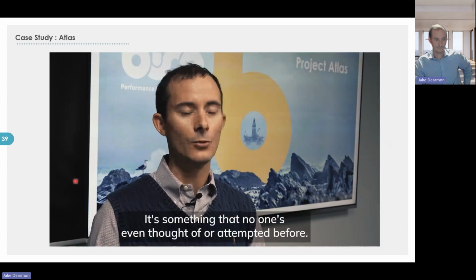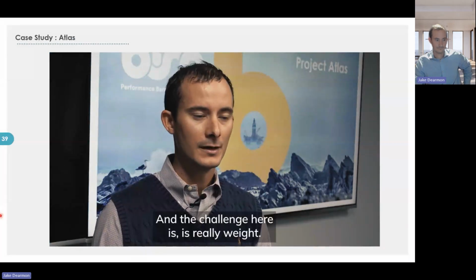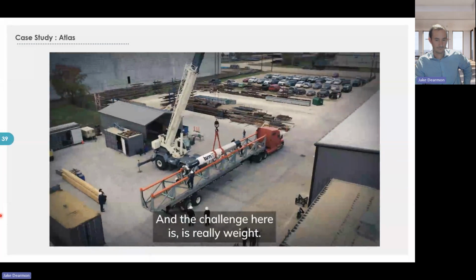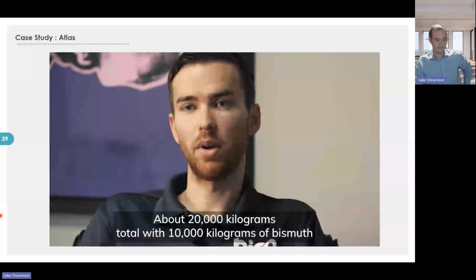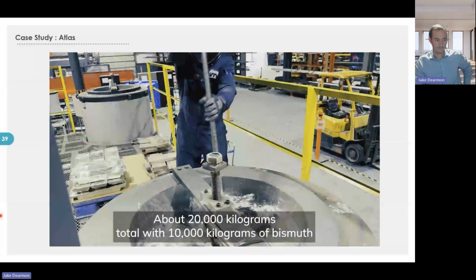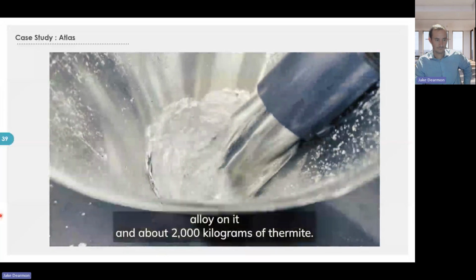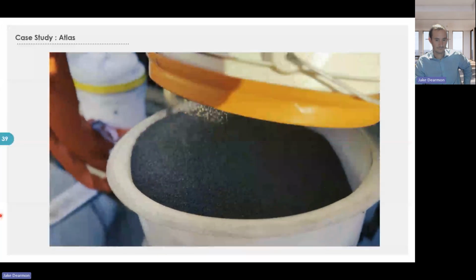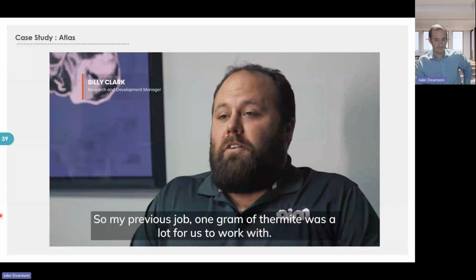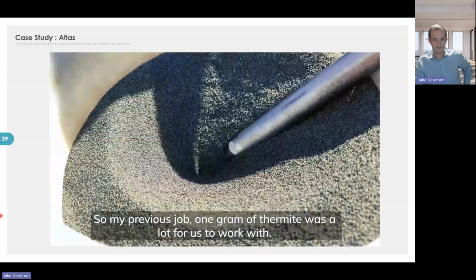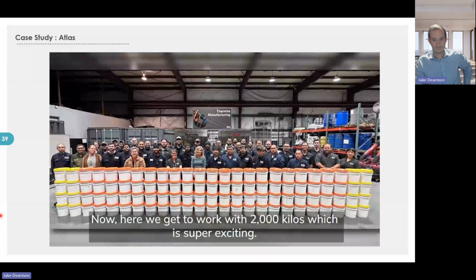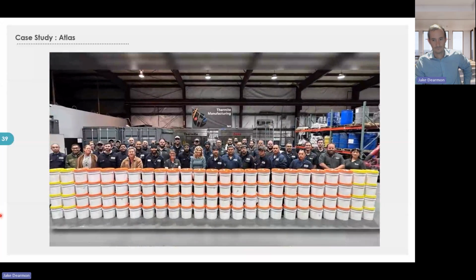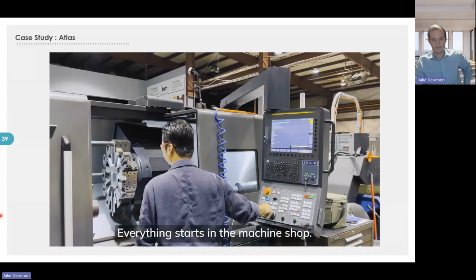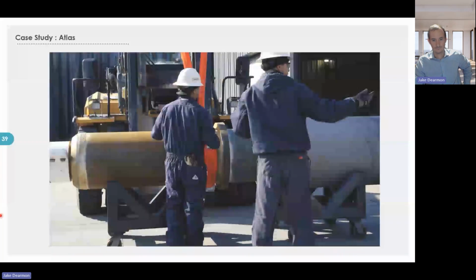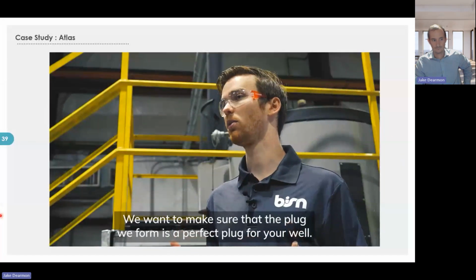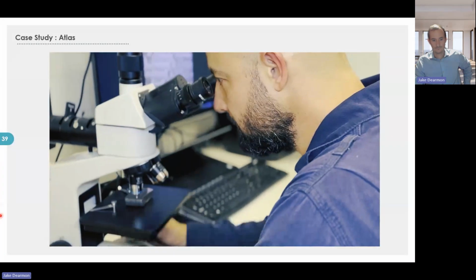It's something that no one's even thought of or attempted before, and the challenge here is really weight. About 20,000 kilograms total, with 10,000 kilograms of bismuth alloy on it and about 2,000 kilograms of thermite. So my previous job, 1 gram of thermite was a lot for us to work with. Now here we get to work with 2,000 kilos, which is super exciting. Everything starts in the machine shop. We want to make sure that the plug we form is a perfect plug for your well.